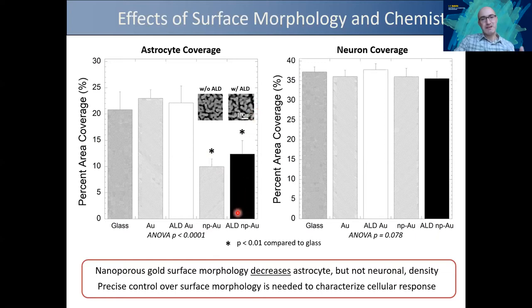But what we did here is we cultured the neurons and astrocytes on a variety of different surfaces and looked at the coverage for astrocytes and neurons. As you can see, for neurons, none of the surfaces had an effect. They were fine attaching on glass, gold, alumina-coated gold, nanoporous gold, and alumina-coated nanoporous gold. But for astrocytes, whether it was coated with alumina or not, for the nanoporous gold, we've seen reduced spreading of the astrocytes, which suggests that it is the topography and not the surface chemistry or silver leaching that has an effect on this. So this is nice because now we have topography to modulate how cells attach onto the surface, preferentially for the neurons.